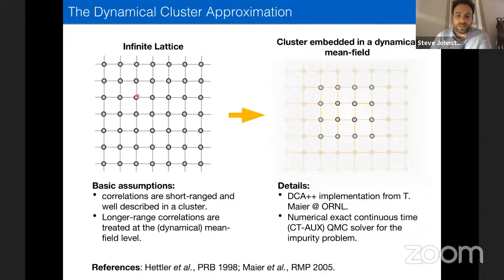The idea is that you're going to take the infinite system and replace it with a small cluster that's embedded in a mean field, but embedded in such a way that the translational invariance of the cluster is satisfied. So the basic assumption here is that the correlations are short-ranged enough that they can be captured on the cluster, or at least the dominant correlations can be, and that the longer range stuff can be treated accurately at a mean field level. And the code that we're using is essentially the DCA++ code, developed out of Oak Ridge by Thomas and his group, using a continuous time quantum Monte Carlo solver.